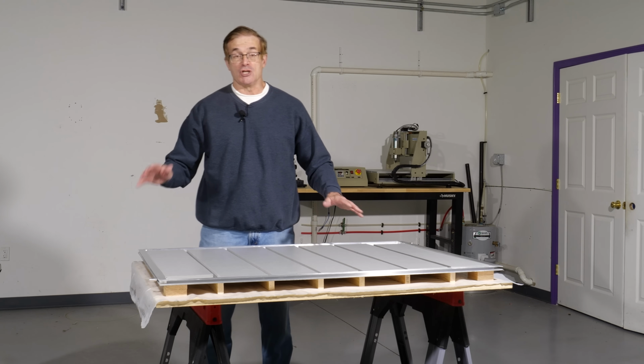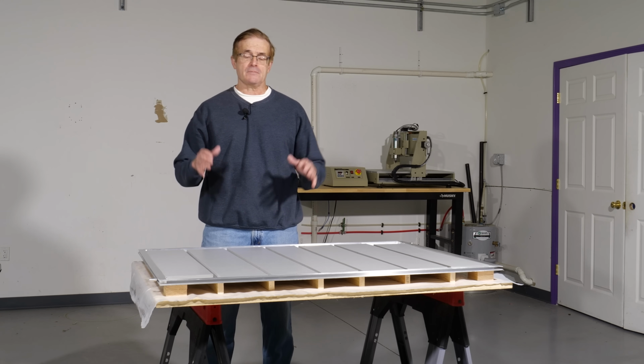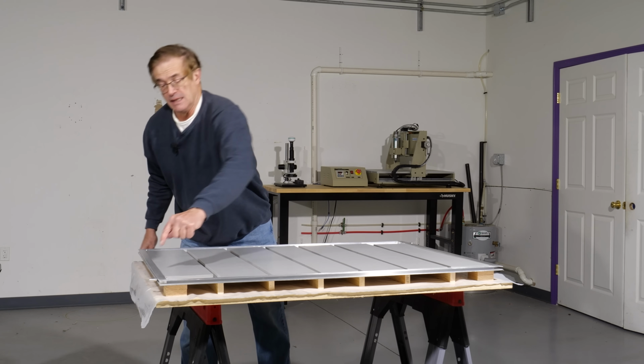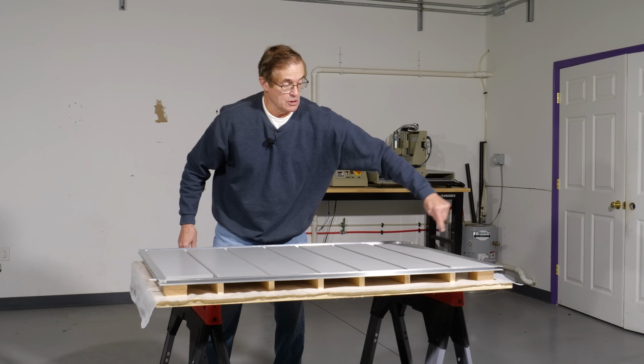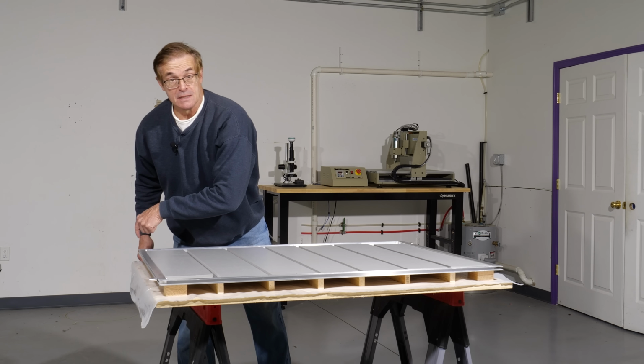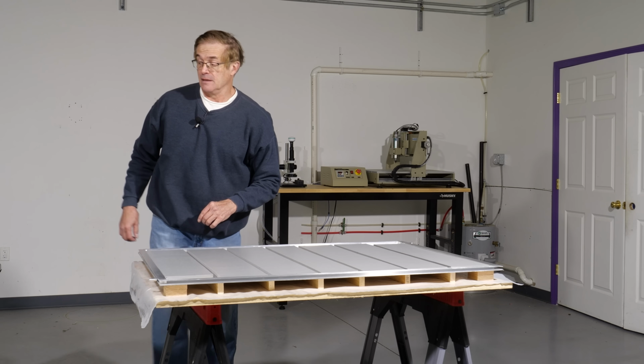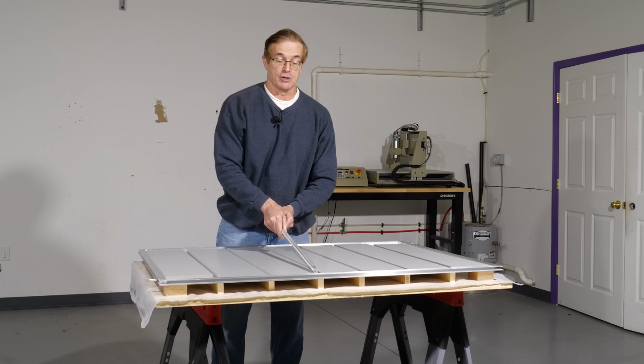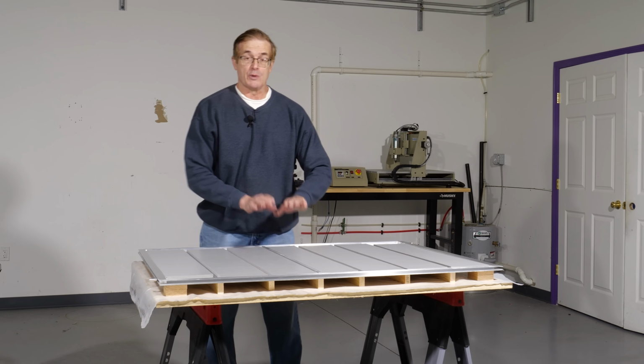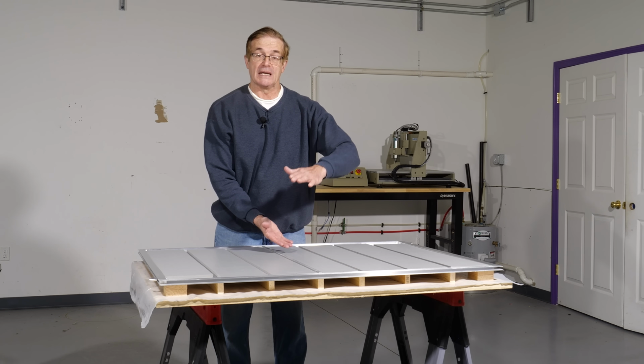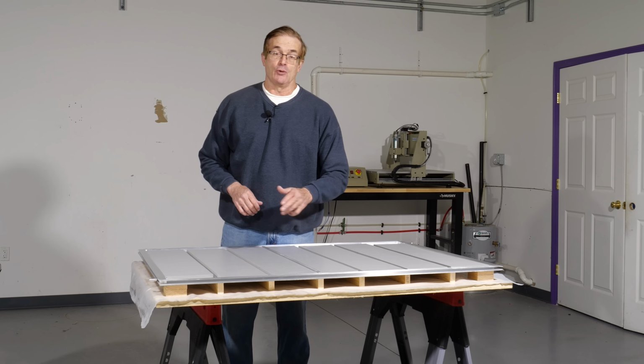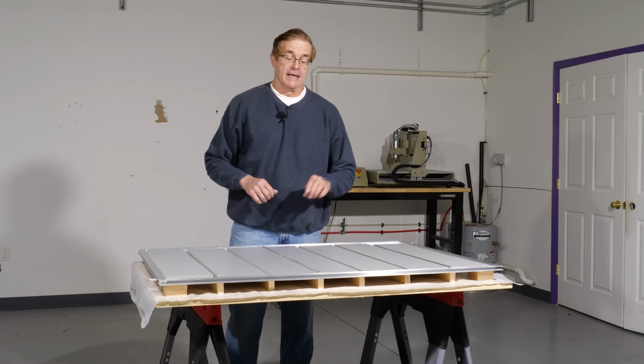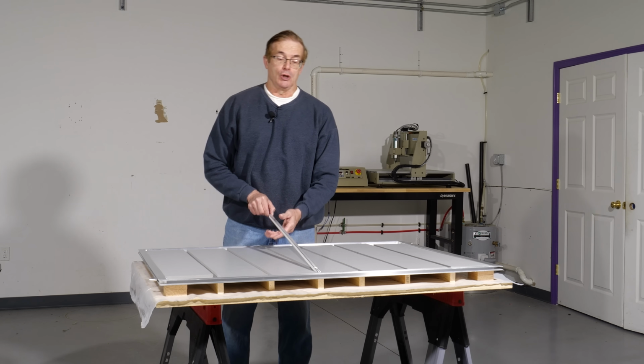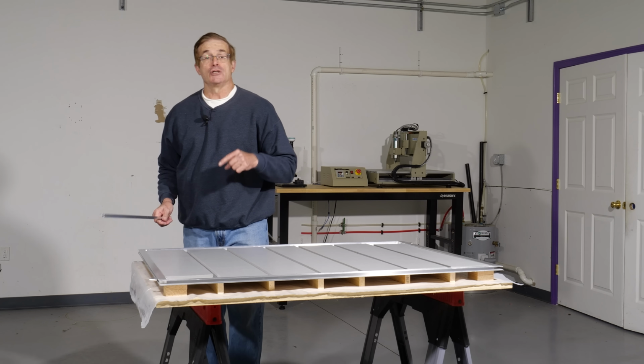Now we could just weld this whole thing together. Problem with that though is it's a lot of welding. You'd have to weld the entire periphery twice. And then we would have to weld in these stiffening ribs that I've placed in between here to provide reinforcements so that the sheets don't balloon in and out with pressure changes. And those aren't visible, so we'd have to do some spot welding. So for this very low load application, we decided rather to use epoxy bonding, and that's how we're going to put this together.